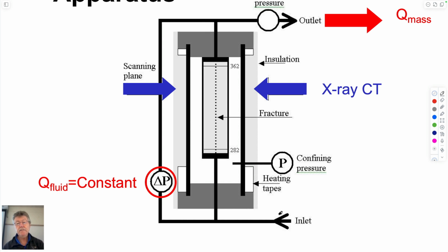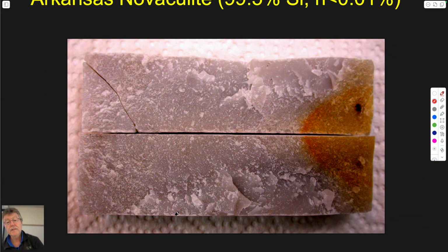You have a pressure in, you have a pressure out, you measure the pressure drop across the sample with a differential pressure transducer, you apply a confining pressure on the exterior. The sample has a fracture along the length of it, which water will flow along. You collect the fluids at the outlet, you measure concentrations to get an assay on the mass that comes out, you try and get changes in porosity from the X-ray CT, and you can use Darcy's law to calculate permeability from measuring the volumetric flow rate as a function of a known pressure gradient you apply across the sample.